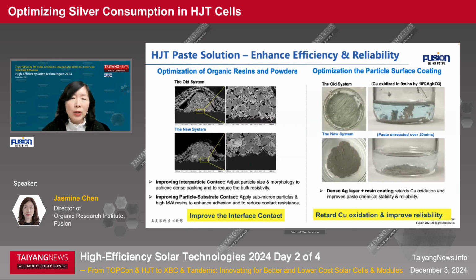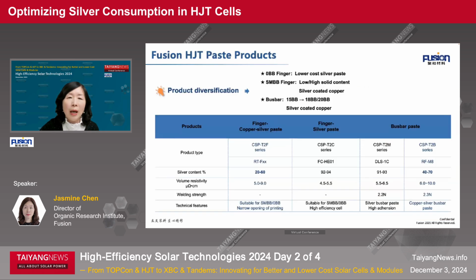Our solution to enhance efficiency is to improve the interface contact. There are two interfaces. One is between particles. The other is between the particle and the substrate, the cell. If we optimize our organic resin and powder to make this contact very good, we can enhance efficiency. Another concern is reliability. After we optimize our particle surface coating, you can see a big improvement in copper oxidation and copper reliability.